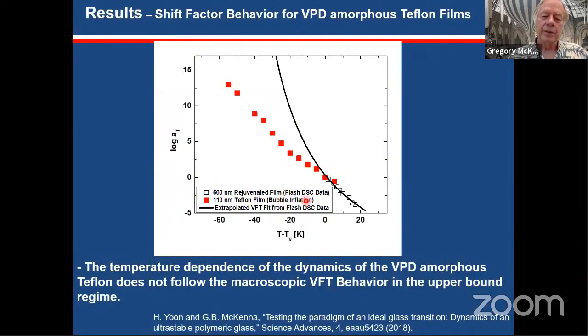And quickly, here's the result. We see here's the equilibrium data. Here's the Vogel-Fulcher fit to the equilibrium data. And here's the actual data in the window where we're in the upper bound condition. And so you can see we got way below the glass transition temperature. And this is very close to the Kauzmann temperature. So all the way down to the Kauzmann temperature, we find that we have deviations from the Vogel-Fulcher in this upper bound condition.